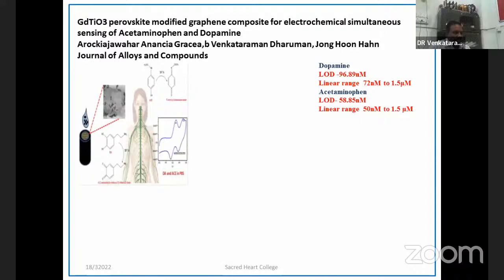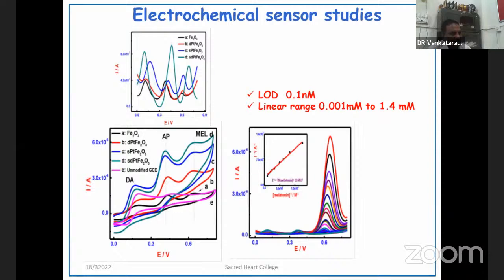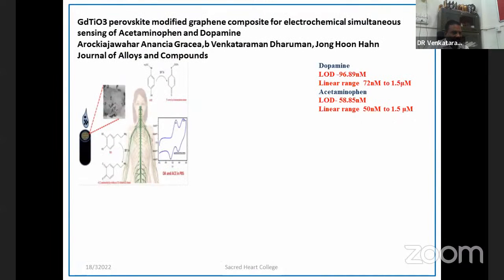So here, we changed to a perovskite material modified with graphene to form a composite, and again we measured dopamine. Here you can see the nanomolar concentration range, with a linear range of 72 nanomolar, whereas in the previous one it is around 1 nanomolar. So when you change the material from a transition metal oxide to a perovskite, with gadolinium, the rare earth material, coupled with the transition metal to form the perovskite, modified on the graphene surface.